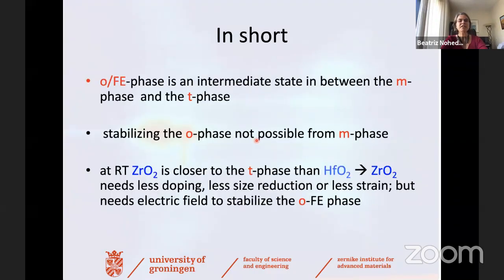So in short, to summarize the introduction, the orthorhombic ferroelectric phase is an intermediate state between the monoclinic and the tetragonal phases that are well known in hafnia. Stabilizing this ferroelectric phase is not possible if one starts from the ground state, so you have to find tricks like size reduction or doping or strain to go into the tetragonal phase or directly into this orthorhombic phase. And at room temperature, zirconia is closer to this tetragonal phase than hafnia, and therefore zirconia will need less doping, less size reduction, or less strain to get into the tetragonal phase. But on the other hand, it needs an electric field to stabilize the orthorhombic phase.